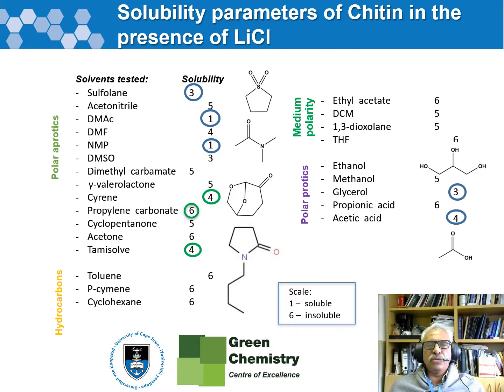So in order to try and get better solvents for the process, we screened a whole number of solvents. We went over to the York University Green Chemistry Center of Excellence, spent some time working on a whole range of solvents, and it happens that the dimethylacetamide with lithium chloride combination worked out as the best solvent for the system.